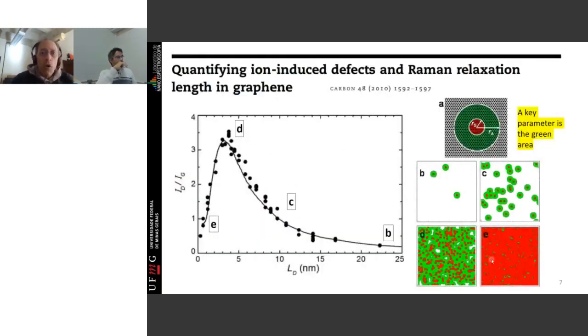And this is one paper that we have in 2010, where we did an experiment that was like this. We took a sheet of graphene and we bombarded it with ions. Okay, so when the ion hits the graphene, it generates a disturbance on a given area that I call this red area here. So this red area is the area that has been damaged by the ion impact. And if you keep bombarding the graphene, you will increase the number of defects up to the point that you completely destroy the material, okay?